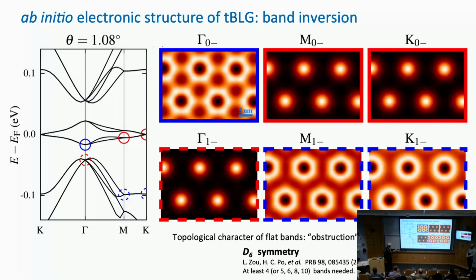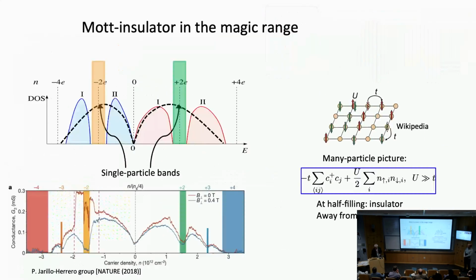So this is what we're seeing here directly from ab initio calculations. In other words, the frustration comes from the fact that if you look at these spots, these are spots in a triangular lattice, but there's no way to produce this kind of band dispersion in a triangular lattice. So there's definitely more to it than that. You can't just stick with a triangular lattice and say, I'm done, this is all I need. That's completely wrong.